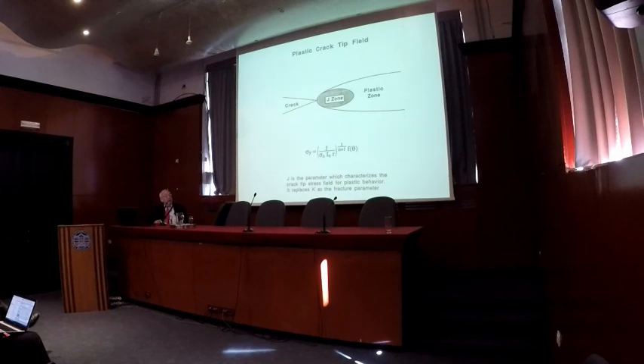One of the things that made J attractive was work by Frank McClintock. I don't know if you all remember Frank McClintock. He was a professor at MIT and had done fracture mechanics work. He said then that you could write the crack tip stress field in terms of the J if you go inside the plastic zone in a way similar to how you would write the crack tip stresses with K outside the plastic zone. But this then gave an idea that the J could be a parameter which characterized the crack tip stress field for plasticity behavior. So it should replace K then as a fracture parameter.